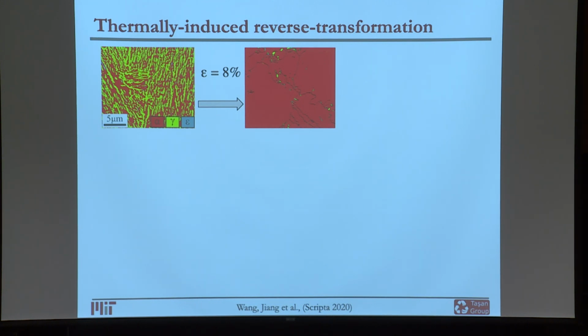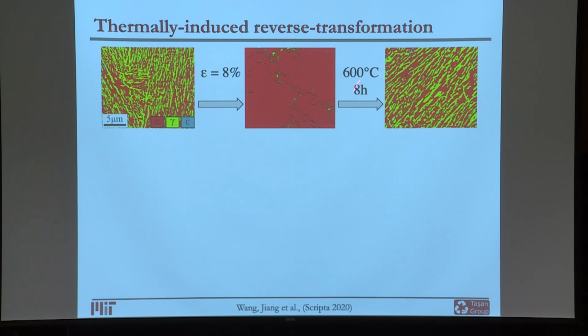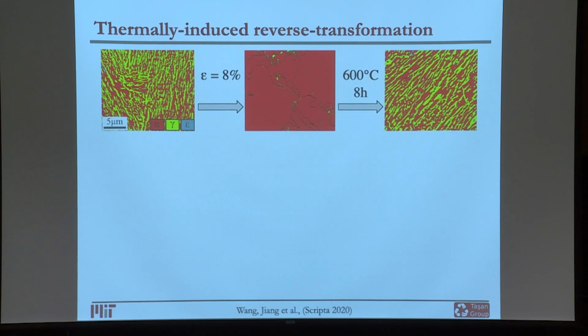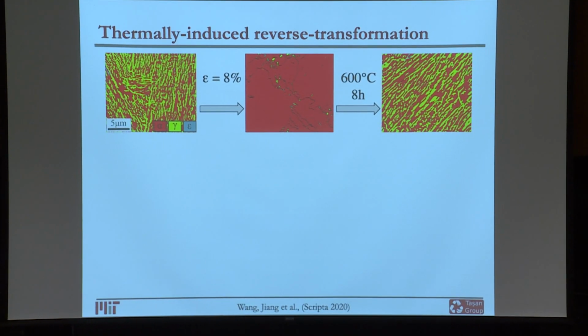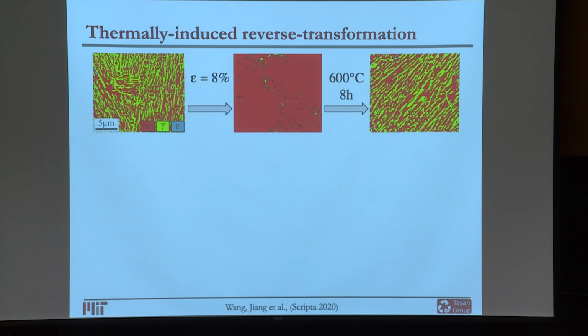So you only see the BCT at this point. And then you apply a heat treatment, and you get to a microstructure that really resembles the beginning microstructure. So here, one might say, well, in metals, we can always do recrystallization. So what's the big news here? The news is related with how close you can get to your starting microstructure.